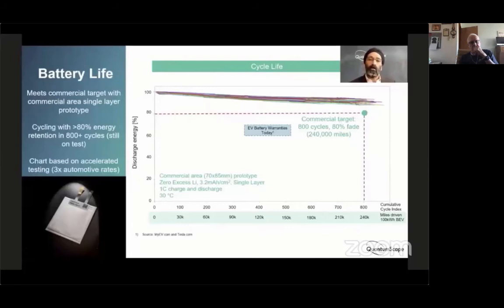No other solid-state battery that we are aware of can, under these conditions, cycle anywhere near this well. And in addition, this is not just one hero cell. This is a whole batch of cells that we made, and as you can see, the batch cycles very reliably. So this is another challenge that solid-state battery companies have, is that you can sometimes make one hero cell that can cycle without shorting, but it's very, very hard to make high reliability batches of cells. And that's what we're showing here. So this really demonstrates that this technology is in fact ready for commercial deployment as soon as we can scale up production and make multi-layer versions of these cells.